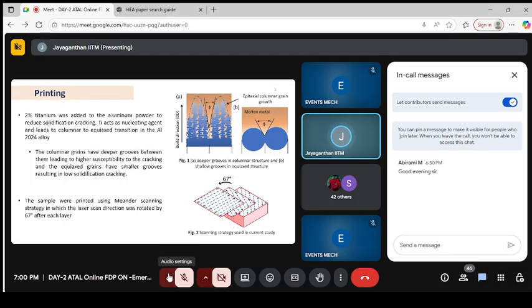If you use pure aluminum 2024 alloy without adding titanium, you have a columnar-like structure, pillar-like structure. And you can see in between two columnar grains, you have the groove, the shallow groove. That is the one being the culprit for inducing solidification cracking. But if you add 2% titanium to the aluminum 2024 alloy, it is refining the microstructure. The so-called equiaxed structure is spherical, with the same dimension in all directions. So the cavity, the groove is completely filled with the molten metal. We end up getting equiaxed structures.